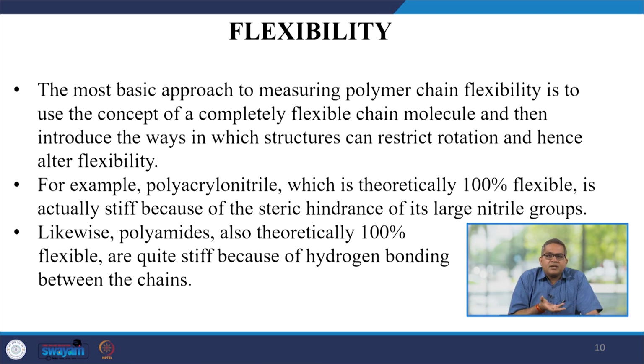So, in a hypothetical way, you have the completely flexible system, and then you restrict the motion of the chains, you restrict the rotation of the chains, and then alter the flexibility, and you measure all these things. Like polyacrylonitrile, which is theoretically 100% flexible, is actually stiff because of the steric hindrance of its large nitrile groups. So, steric hindrance causes the stiffness.